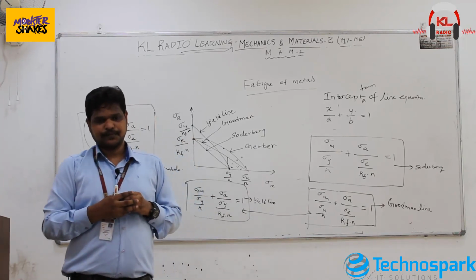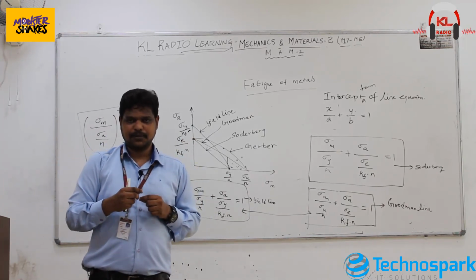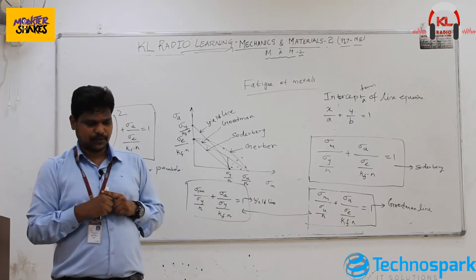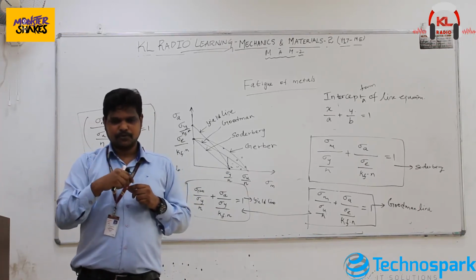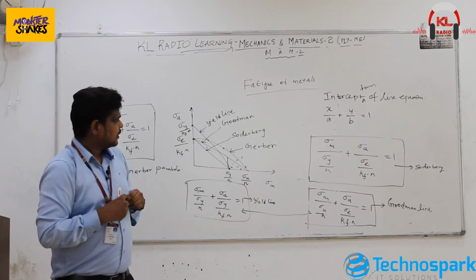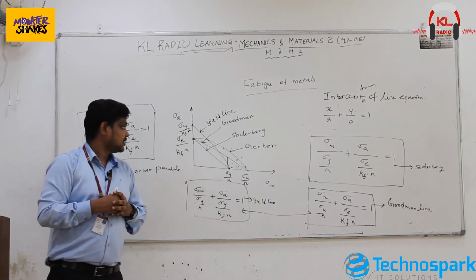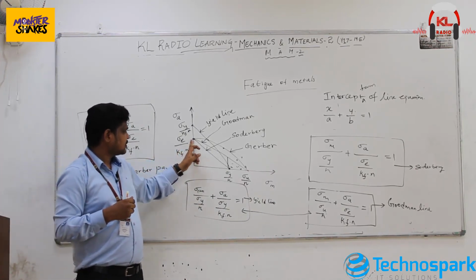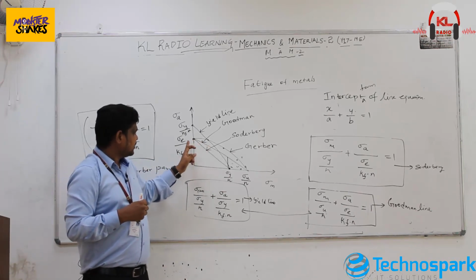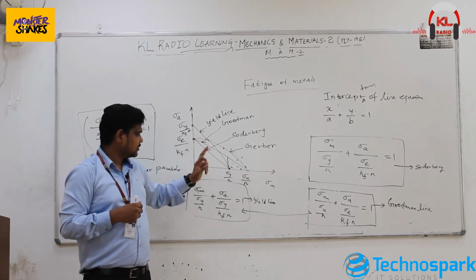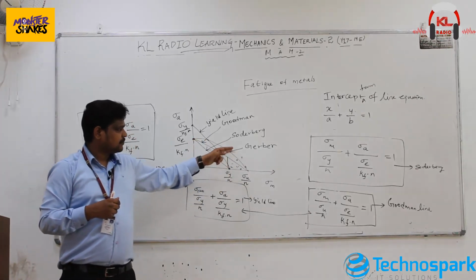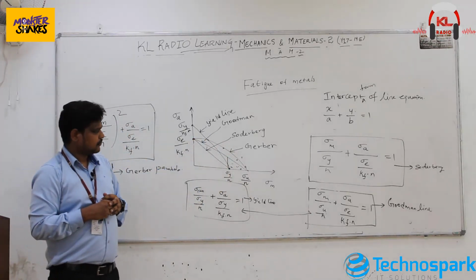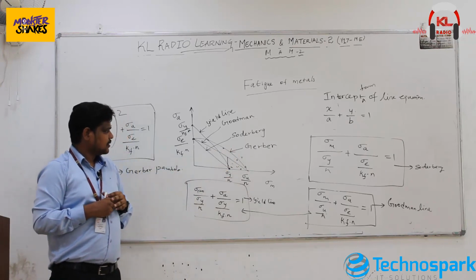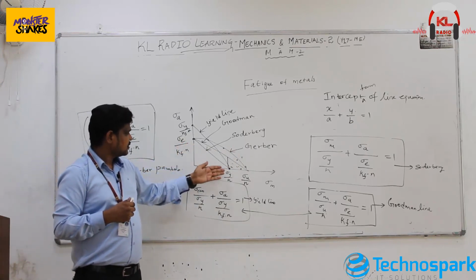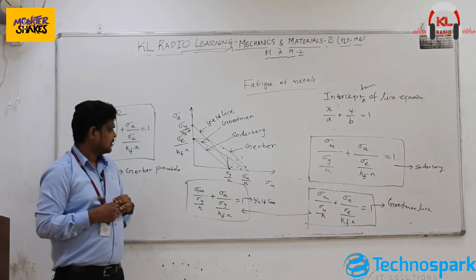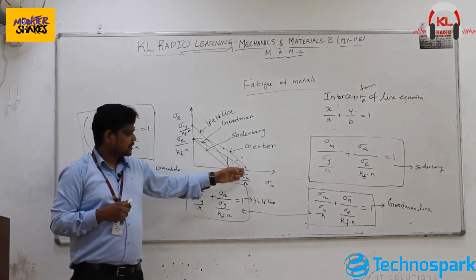Similarly, for a machine component subjected to a fluctuating load which is superimposed by the mean stress, a few scientists have proposed lines from the test data which fall between the endurance and ultimate. With the test data, Gerber has proposed a parabolic curve, and some scatter in the result is there. Soderberg has proposed a line from endurance to the yield, and Goodman has proposed from endurance to ultimate.